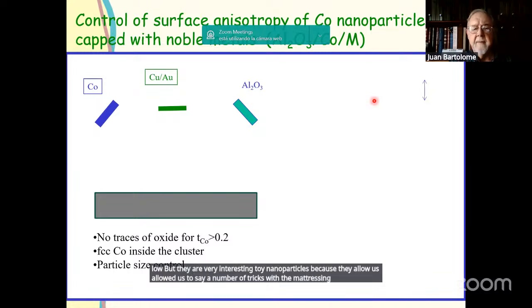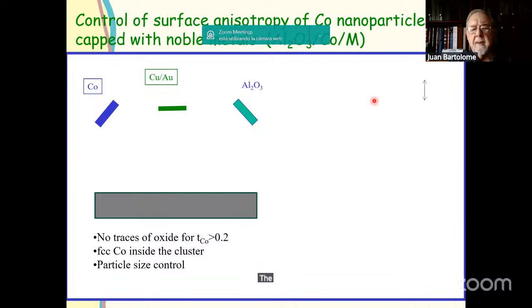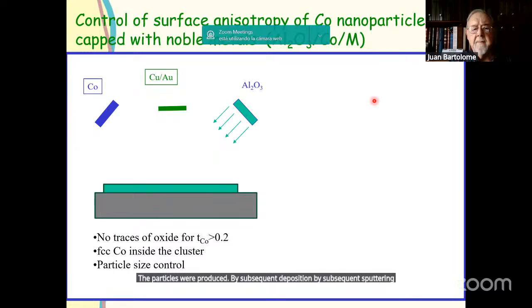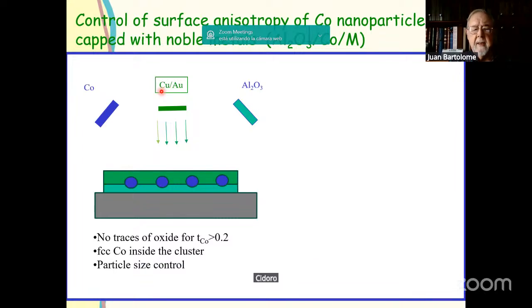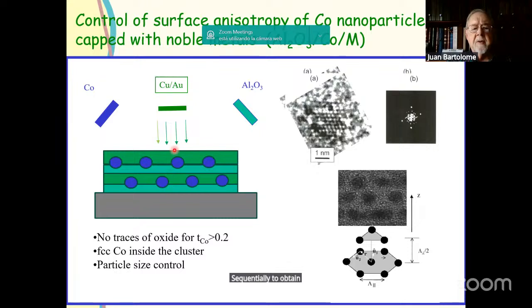where they were sitting. The particles were produced by subsequent deposition by sputtering of amorphous alumina, then cobalt, then they self-organized into spheres of a diameter that depended on the time of sputtering. Then we could cap them with different metals. I shall be speaking of copper, silver, and gold, and others. And then we can proceed sequentially to obtain up to 25 layers.